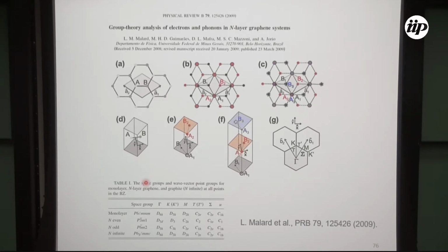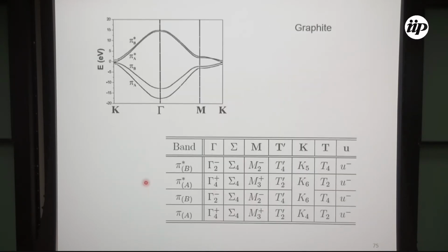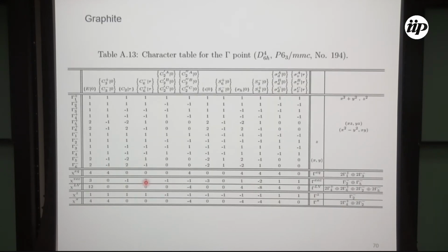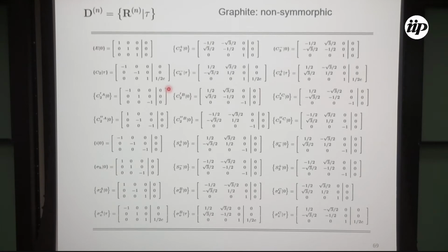Once you have a space group from which you can factorize all lattice translations, the resulting factor group is a point group, and then you always work with the point group. In some groups, you have translations that are not lattice translations. They are fractions of the lattice translations. In these groups, you cannot factorize these fractional translations, and these are the non-symmorphic groups.